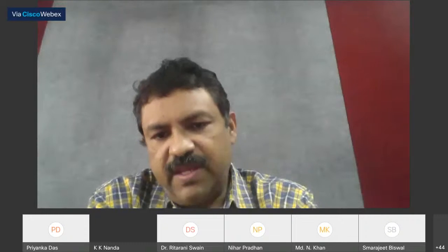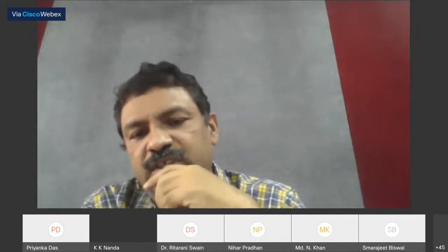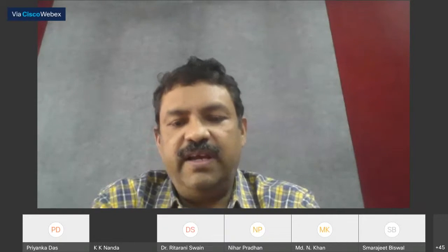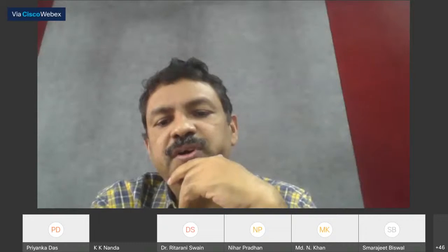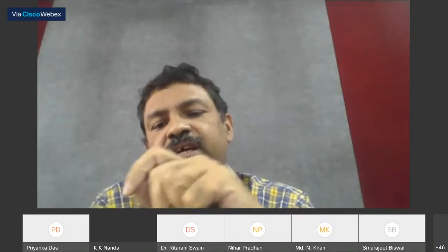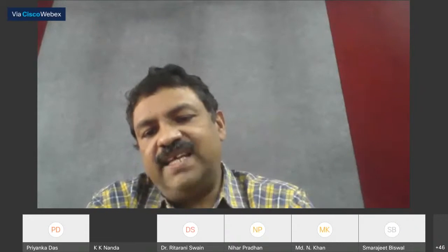Yeah. So, coming back to the work on nitrogen-doped carbon nanotubes. If you replace one carbon by nitrogen, nitrogen being more electronegative, it will be negatively charged and carbon will be positively charged. When any oxygen molecule comes in the vicinity of the nitrogen-doped carbon nanotube, carbon being more positive because of the nitrogen in the vicinity, oxygen becomes slightly negative and prefers to get attached.